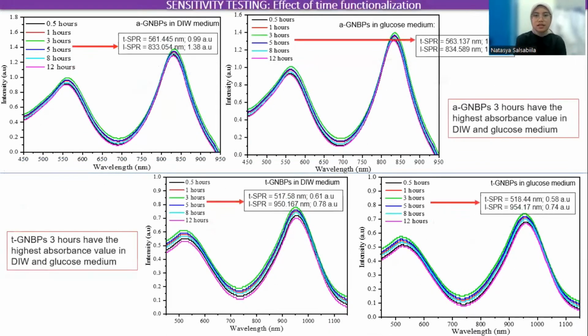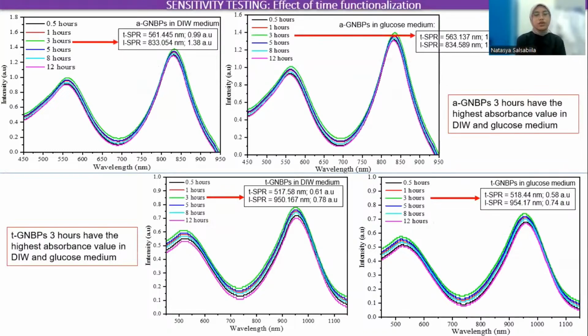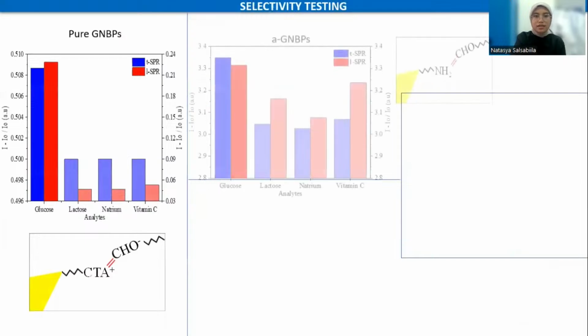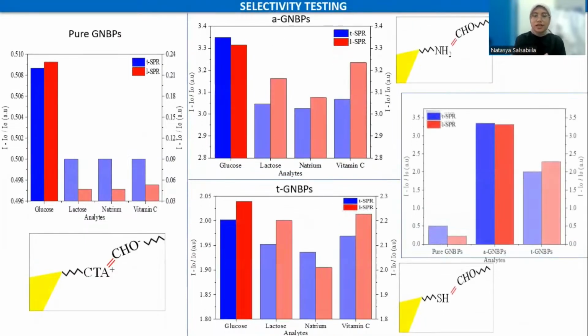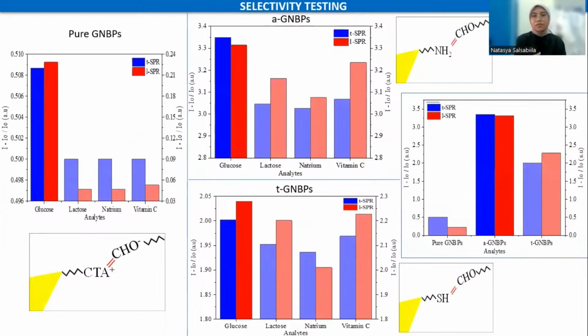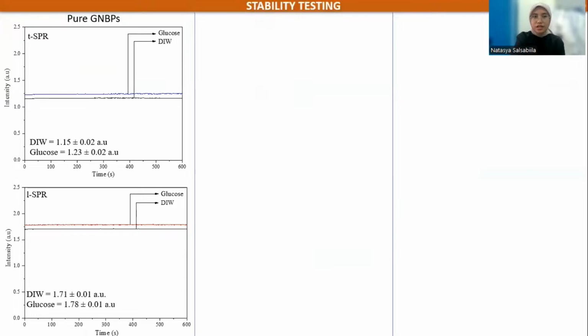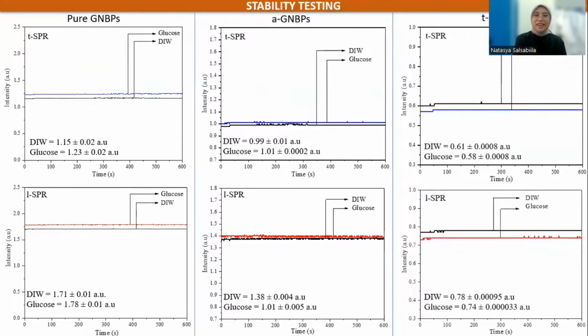Based on this result, 3 hours of A-GNBPs and T-GNBPs produce the highest signal response compared to the others, denoted by the highest intensity change value. And this is the selectivity test of pure GNBPs, A-GNBPs, and T-GNBPs. If you see here, A-GNBPs and T-GNBPs perform a higher selectivity response than pure GNBPs, with A-GNBPs being the greatest one. Then we test the stability for pure GNBPs, A-GNBPs, and T-GNBPs. We can see here that A-GNBPs and T-GNBPs produce a higher stability response than pure GNBPs through a lower error value, with T-GNBPs producing the greatest stability response.